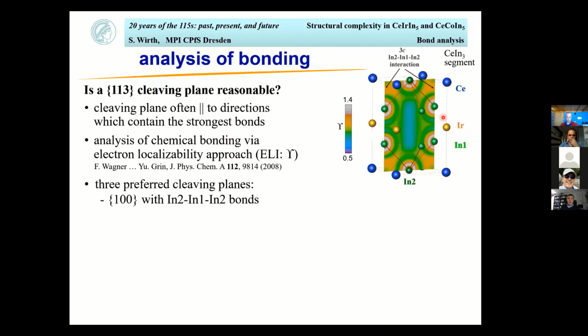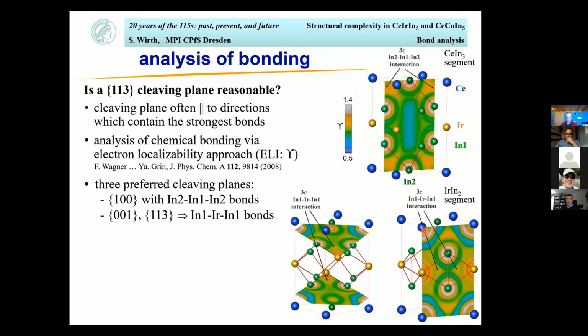Now here, what he found is that actually there are three preferred cleaving planes. One involves only the indium bonds. So you have here the in-plane and the out-of-plane indium. And look at these yellow spots. This is where most of the localization takes place. This is where the bond takes place. But this is actually best seen here, where we see the IrIn2 segment. And if you look here, within the iridium, we have also some bonding. And you see that this actually is the 001 plane in this case, because this is in the plane outlined by the 4 iridiums. You don't see the one on the back.